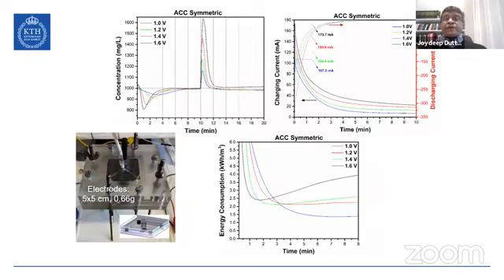One can play with other configurations as well. One can have a symmetric configuration like any electrolytic capacitor, or an asymmetric configuration. I would like you to note the concentration curve here. The concentration here means the ionic concentration in water, and with increasing voltage, we see that the ion concentration reduces more steeply. In other words, one can do multiple cycles within a period of time to increase the throughput, with asymmetric electrodes as well as with symmetric electrodes.